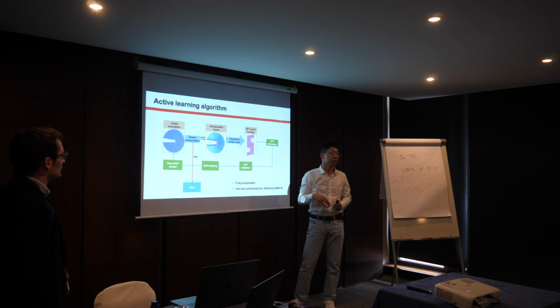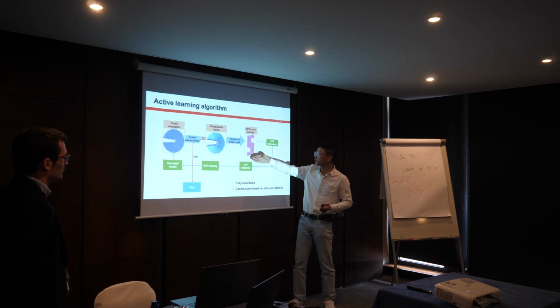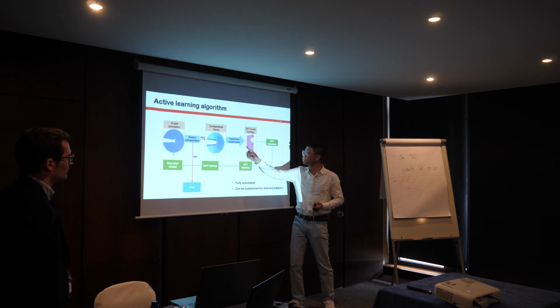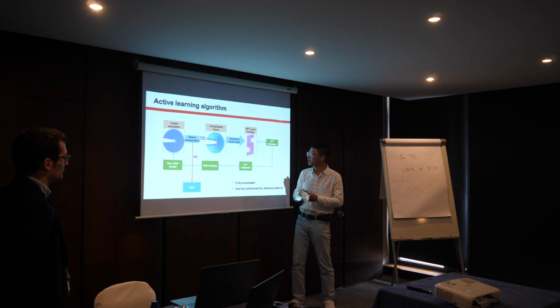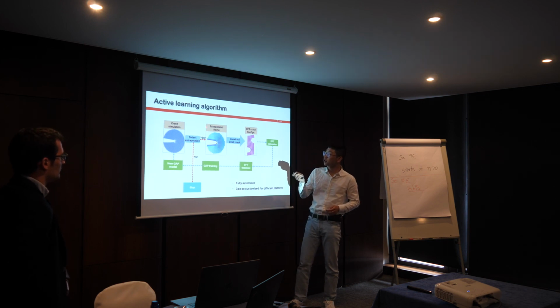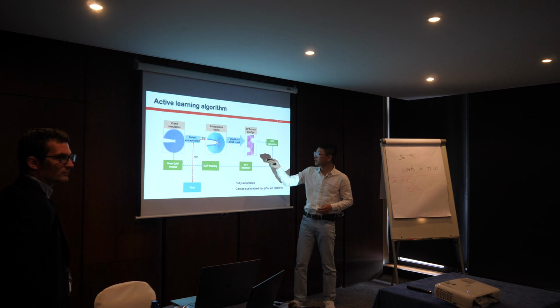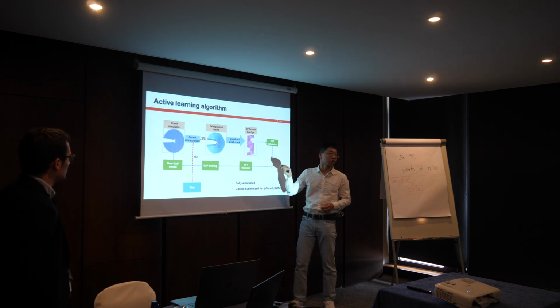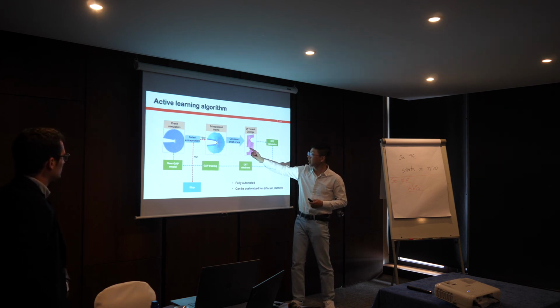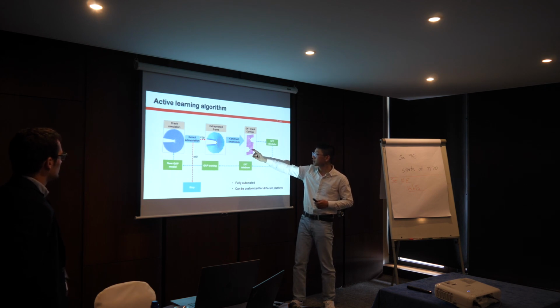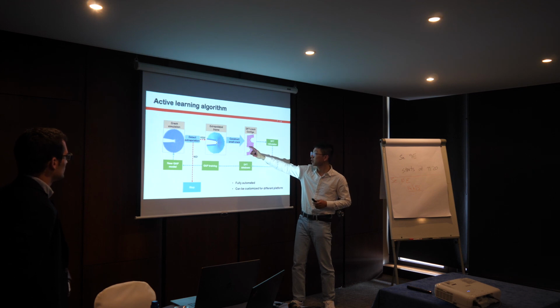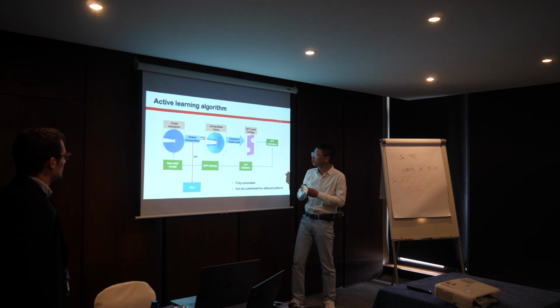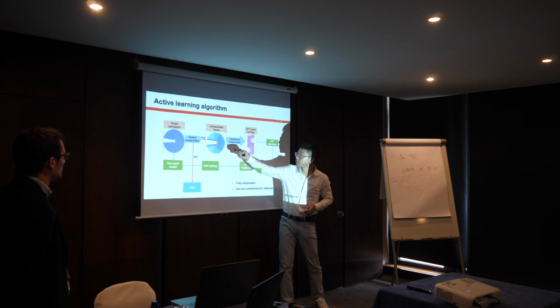The boundary condition of a DFT code, if you don't set it, is always periodic. So you would have a surface here, but the benefit of the machine learning potential is that you have a localization assumption, which means this atom is only assumed to interact with atoms within the cutoff radius.